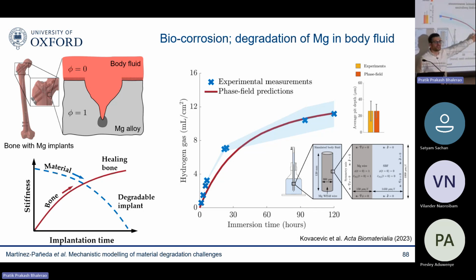And the problem with magnesium is that it degrades too fast. Magnesium is the most promising candidate, but it degrades too fast. So we need to understand the corrosion of magnesium. So for that, we again extended the model.